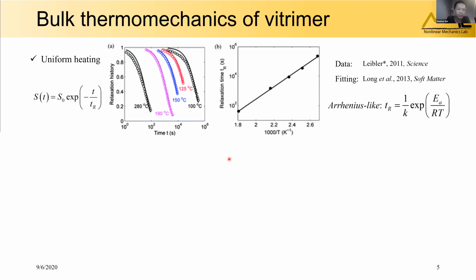For the bulk Vitrimer behavior, the previous studies have focused on the uniform heating case. Since the reaction kinetics are governed by the Arrhenius law, the material also exhibits Arrhenius-like temperature-dependent relaxation behavior. That is, the relaxation time scales with the exponential of 1 over temperature T. Long in 2013 developed a constitutive model for the Vitrimer, which can capture the experimental behavior of the Vitrimers. However,